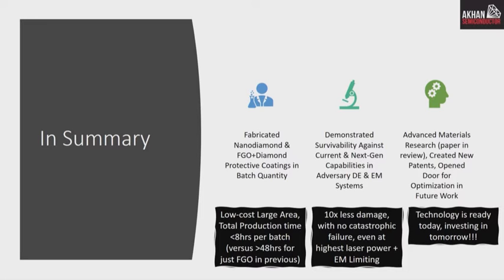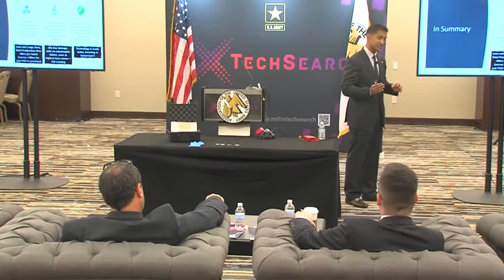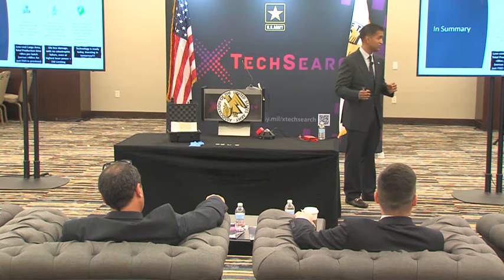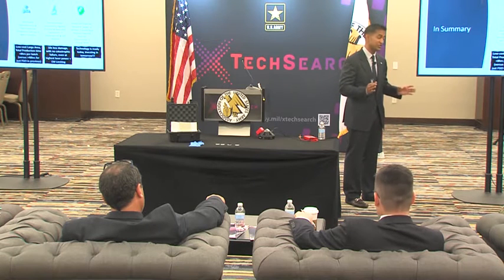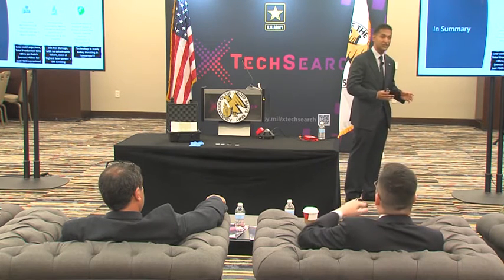We did this using a low-cost, large-area system, and again, using chemical dispersion or spin dispersion for the graphene oxide. It's a very cheap and highly scalable way to do such. Again, we reduced the total production time from 48 hours for the FGO down to less than 8 hours per batch for the entire production of this part. So as it stands today, it's highly, highly manufacturable.